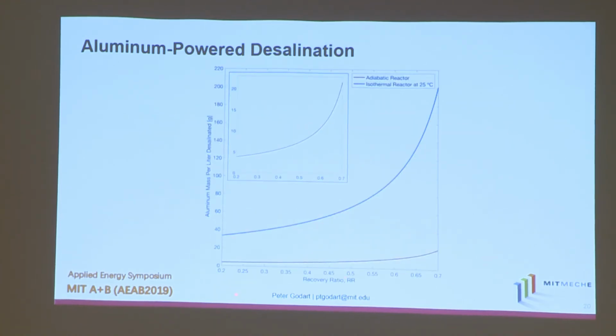This plot here shows the amount of aluminum required per liter of seawater desalinated, 3.5% salinity seawater, as a function of recovery ratio. That's how much water we extract from how much water we put in there initially. It's because it's a batch process. And these curves represent the upper and lower bounds of that system depending on how well insulated you can keep that piston. We show that blown up here is the lower bound, and we show that for low recovery ratios, we're hovering around 5 grams of aluminum per liter desalinated. 5 grams of aluminum is less than half of an empty soda can's worth of aluminum.